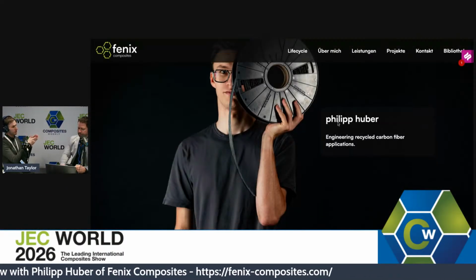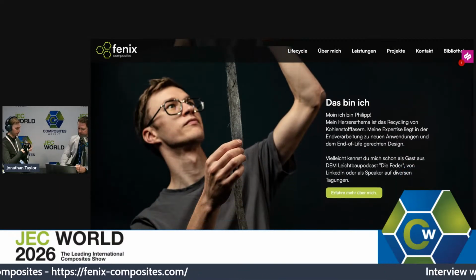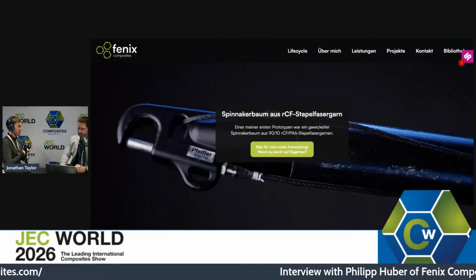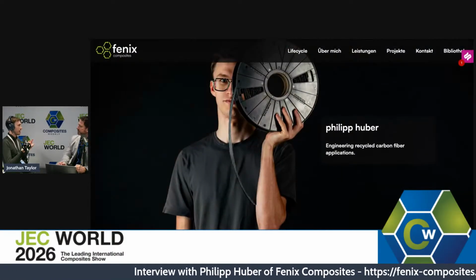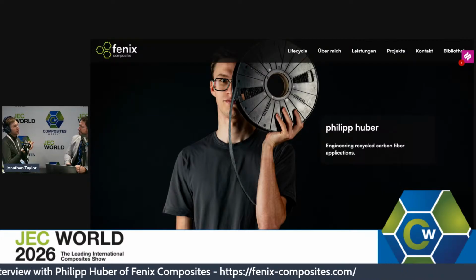One of the key advantages is that the joints are really, really strong. I think the reference value for adhesive bonding is 13 megapascals of shear strength, and we managed to achieve over 50 megapascals with nylon 6. So we are far above the industry standard, and this means you can create shorter overlaps. Actually, we have this tie rod, and the overlap is so short that you really need to be careful that your insert doesn't tilt while putting it in, because when it's longer, it aligns itself. And the other thing is the cycle time. We heat for maybe 2 to 3 seconds, and then the part needs to cool down, and then it's ready to use.